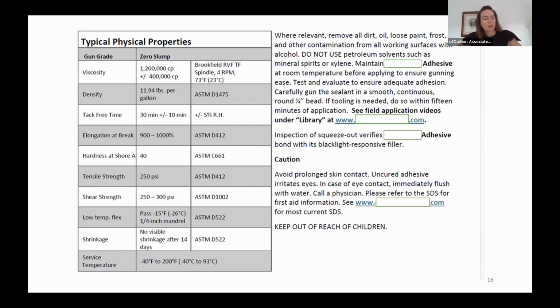But importantly, where before inspectors can count nails but not see necessarily a bond line, with that 1/4 inch bond line, we do produce ample squeeze out, as you've seen a little bit from the video. And importantly, verify, not only see the squeeze out, but that it's ours, because we have a black light responsive filler that shows that it's this particular adhesive or sealant.